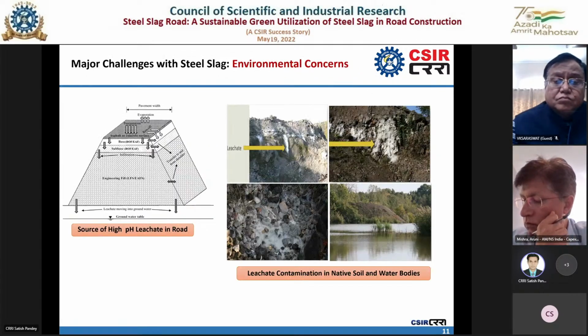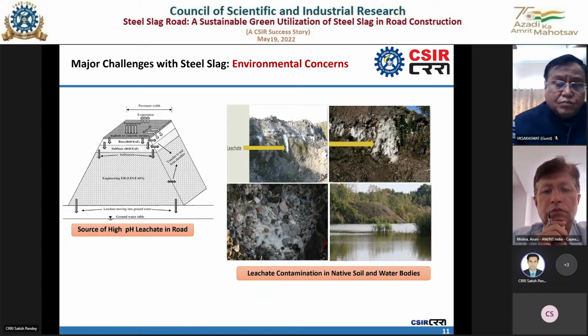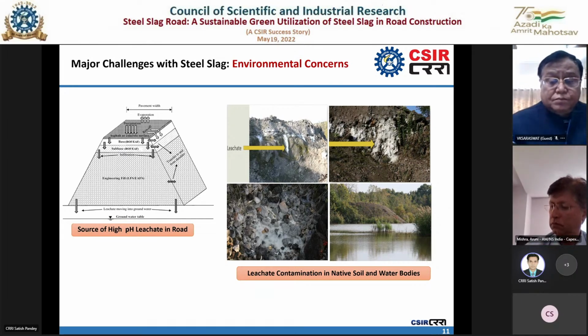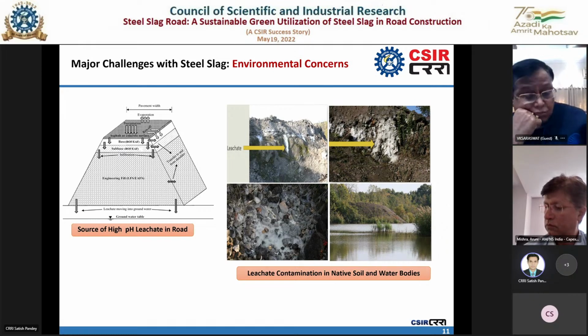Last but not least, another challenge is the possibility of heavy metal leaching. In case unprocessed slag is utilized in bulk quantity for pavement construction, there are chances that high pH leachate can emanate from the deposits of slag and contaminate nearby water bodies as well as land. But when processed steel slag, which has stable mineralogical phases, is utilized for construction, the aggregate does not show any leaching under adverse environmental conditions. We conducted the TCLP test with the help of the National Environmental Engineering Research Institute, NEERI, Nagpur, and none of the processed steel slag aggregate exhibited any heavy metal leaching during testing.